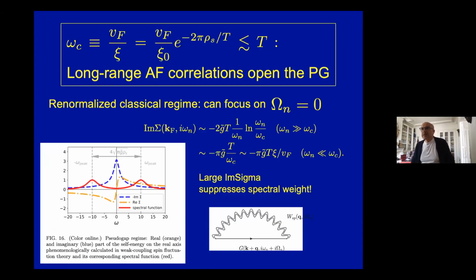The way this happens, how this growing correlation length does open a pseudogap, was explained by Vilk and Tremblay a long time ago. If you actually evaluate the imaginary part of the self-energy with a growing correlation length at a hot spot of the Fermi surface, and here, because it's perfectly nested, the whole Fermi surface is hot, actually, you find that when the correlation length becomes larger than the thermal de Broglie wavelength, the imaginary part of sigma becomes extremely large, of order T xi over Vf. So observe that this is larger than 1 when xi is larger than Vf over T. And that is the phenomenon which is responsible for the pseudogap. This is exactly what we see in our simulations.